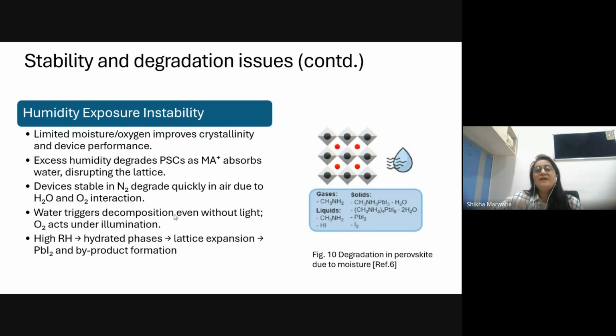Another is humidity exposure instability. Here also, when we expose this material to humidity, near about 85% relative humidity at a thermal temperature of 85 degrees, there are again certain issues reported, and that degrades our methyl ammonium lead iodide.